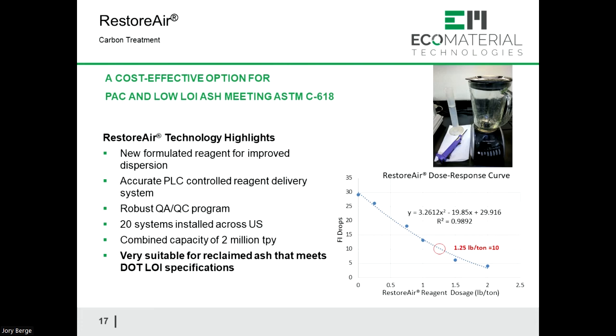I'm going to run out of time, but one of the things I had mentioned earlier was the chemical passivation of the carbon content. And you can kind of see the bottom right chart shows you in a polynomial curve, as you add this chemical to the ash in pounds per ton, it brings down that foam index number. And the foam index number is just generated by a mixture of ash, water, and you add AEA until you get a stable foam for an extended period of time. And this is what's good for those lower LOIs if you still have activity.